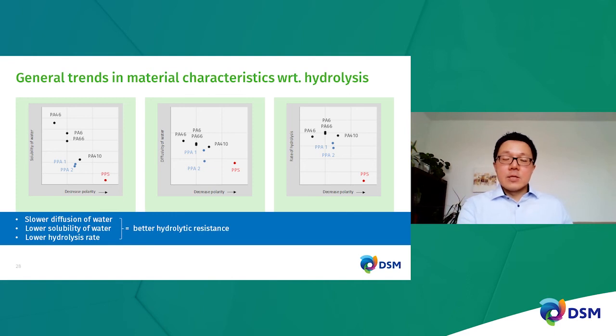In the previous slide, we discussed these important parameters for diffusion and also for the rate of reactions. And these slides show you a little bit more of a summary of what we do in terms of hydrolysis. So the left-hand side figure shows the solubility of water as a function of decreased polarity. So from left to right, you have polymers with decreasing levels of polarity. So from polymer 4,6, which is very polar, to PPS, which is the least polar of the polymer grades that we have in our portfolio.